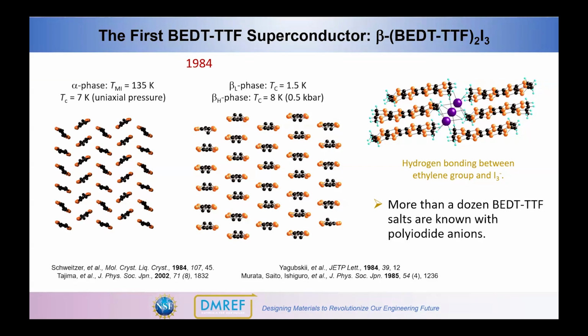So the first organic superconductor based on ET was discovered in 1984, really with two phases of the ET-I3 material. The alpha phase has a metal-insulator transition at 135 Kelvin, whereas the beta phase, as synthesized, has a TC of 1.5 Kelvin, but when you apply slight pressure, half a kilobar, the TC goes up to 8 Kelvin.